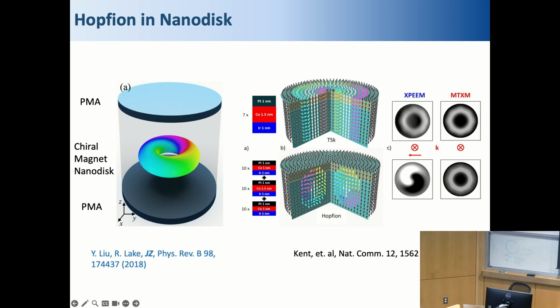Is the hopfion realized in a heterostructure that's composed of multiple versions of the heterostructure that stabilizes? Yeah, you just stack them on top of each other. They have the same stacking sequence, but the thickness of this cobalt layer is different. And then the hopfion extends through many layers. Yes, through many layers. And in the top layer for this combination, there's a large anisotropy, so this part is basically polarized, but inside is a complete distribution of spin.